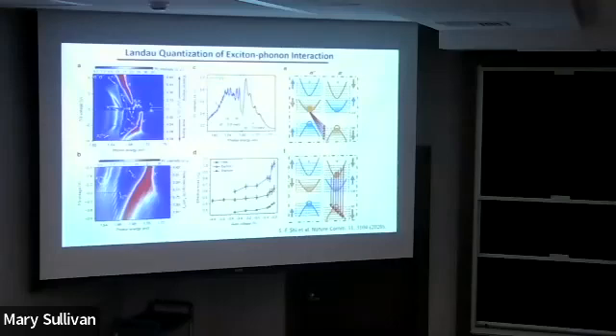If you turn on the magnetic field, you have Landau levels forming in the conduction band and in the valence band. You see the ripple here. There's a ripple from a trion. There's a ripple from the dark exciton. It's very periodic. The spacing here is roughly half of this. What's this peak? Essentially, with this one, you have a very selective Landau level transition, which was done by Chanwei probably 4 or 5 years ago. So we know the transition, how it looks. If you have Landau levels, you are going to have this transition, which matches these ripples.